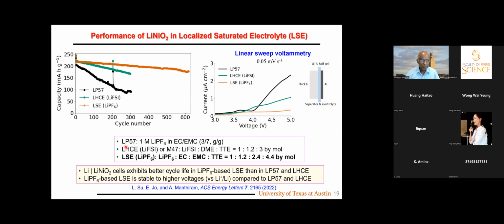So 3 electrolytes: LP57, the conventional electrolyte; LHCE, localized high concentration electrolyte. Compositions are given here. That was developed by PNNL, Pacific Northwest National Lab, as part of the Battery 500 consortium. I am part of that consortium. The third electrolyte, we call it localized saturated electrolyte. 2 advantages here. It uses the carbonate, so it has higher voltage stability. Second, LiFSI is no longer necessary. We use LiPF6 here, and TTE is the diluent. So the compositions are given here.